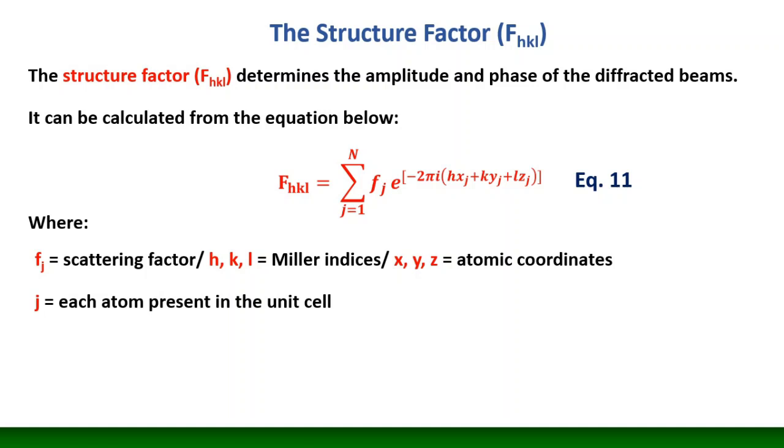For instance, the 8 corner atoms in a BCC unit cell have the same equivalent position. They're equivalent lattice positions. So in the BCC, you would have 2 atoms that we're going to count: one corner atom, which will be representative of all eight, and one central atom located at the central lattice position. So for BCC, that summation would go from J equal 1 until J equal 2.